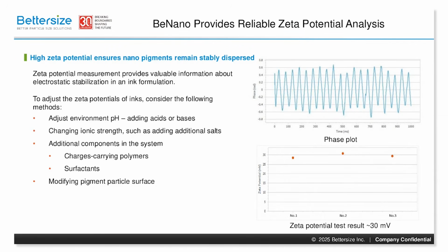Knowing the zeta potential lets us make targeted adjustments for ink stability. We can make the adjustment in several ways. For example, in water-based inks, we can change the environment's pH by adding acids or bases, which alters the surface charge of the pigment particles. Or we can also change the ionic strength by adding salts. This affects the double layer around the particles.